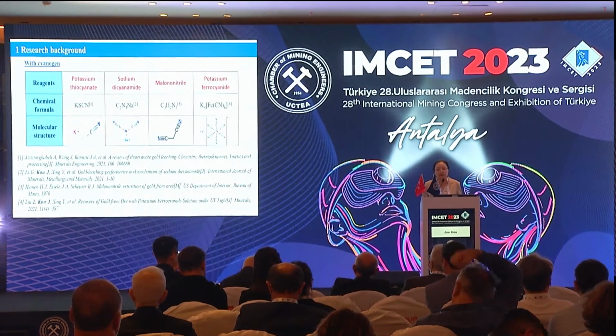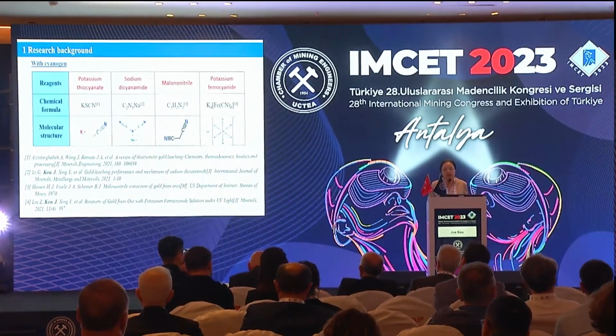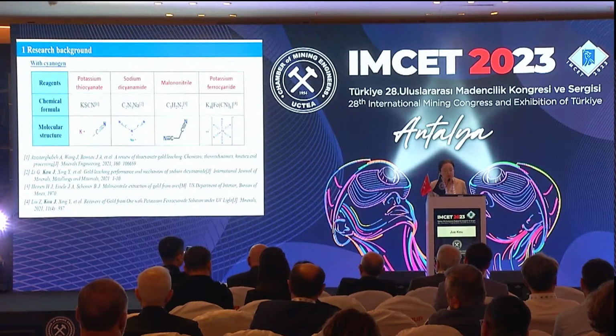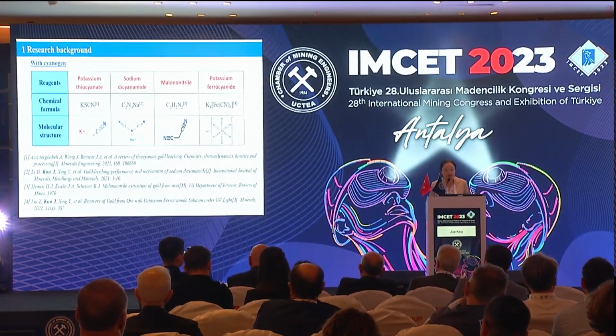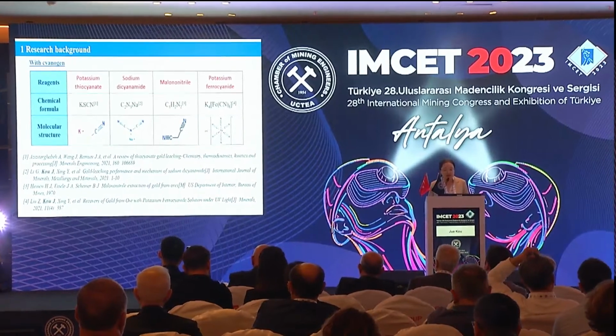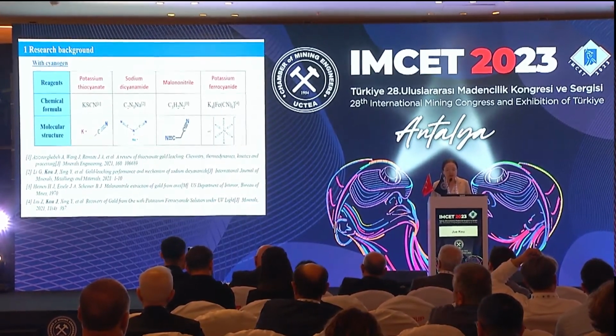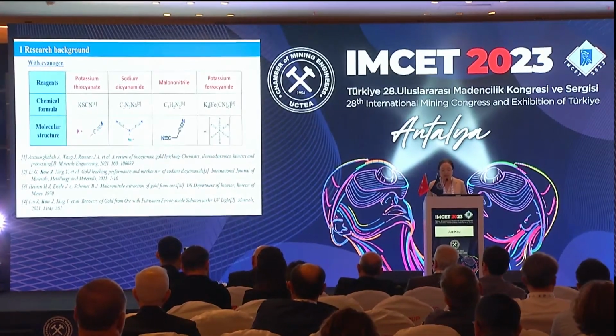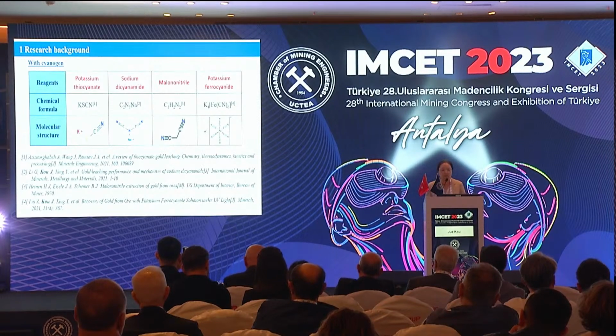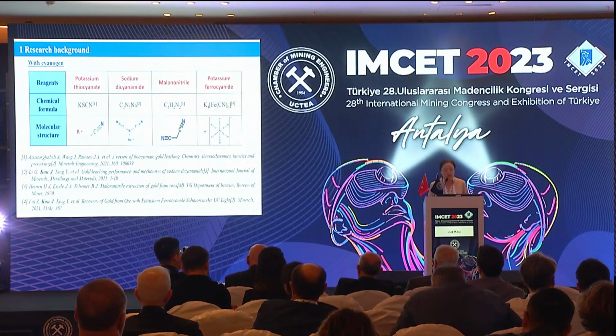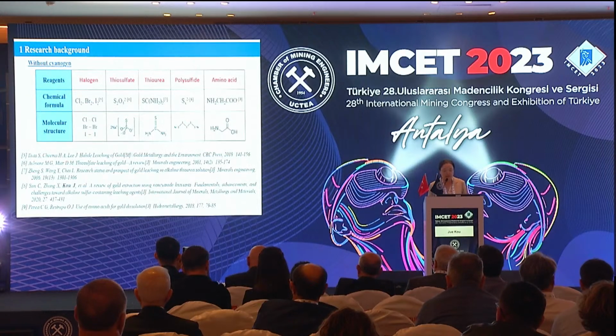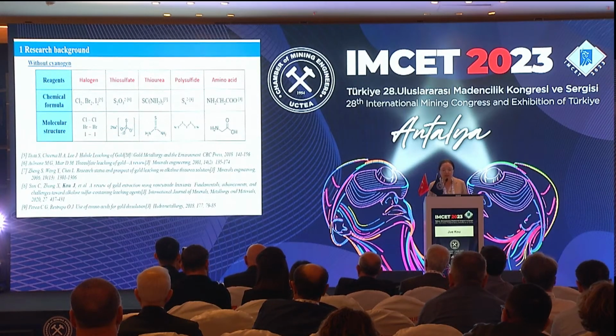So all these low toxicity lixiviants can be roughly divided into two groups. One group is the reagents with cyanogen, such as potassium thiocyanate, sodium dicyanamide, and potassium ferricyanide. And these reagents are all proved to have good gold leaching capability. And there are also some literatures we have published for the research of these reagents. And the other group, without cyanogen, such as halogen leaching, thiosulfate, thiourea, polysulfide, and amino acid.